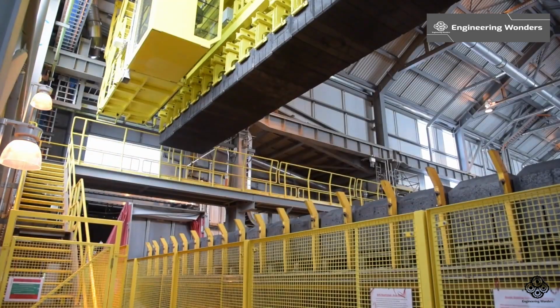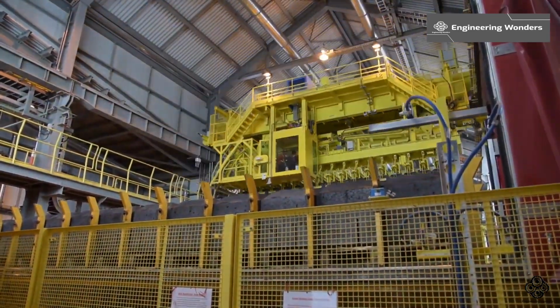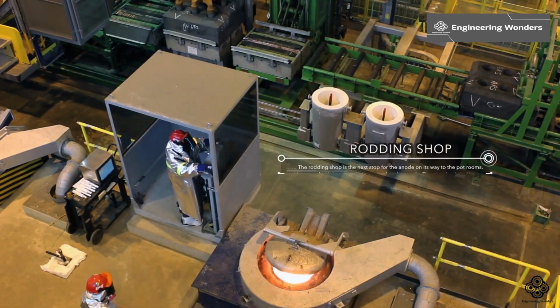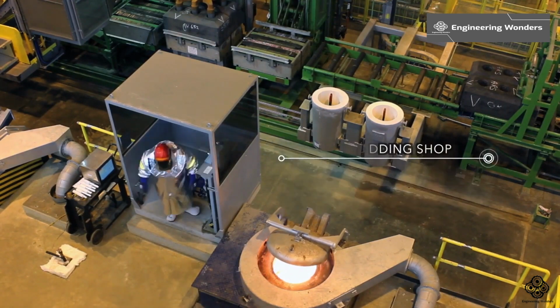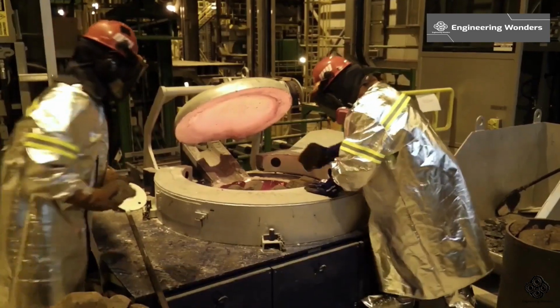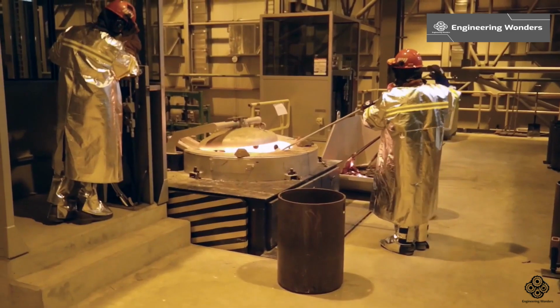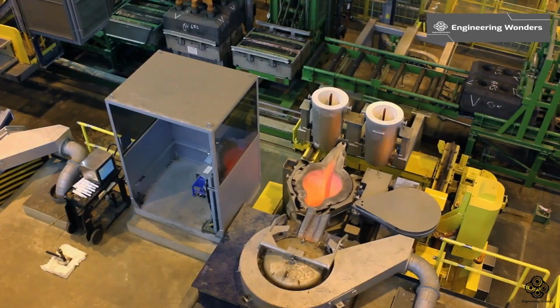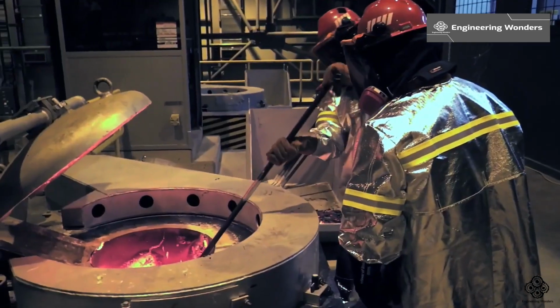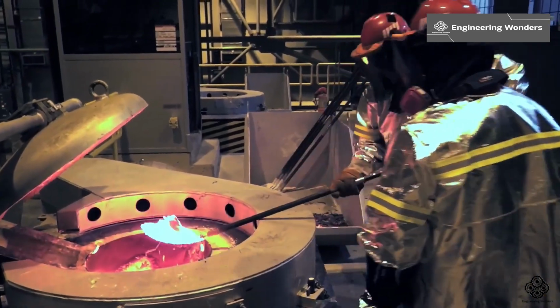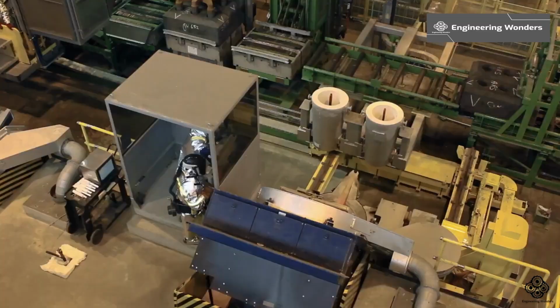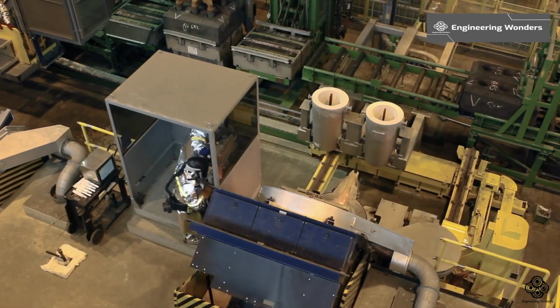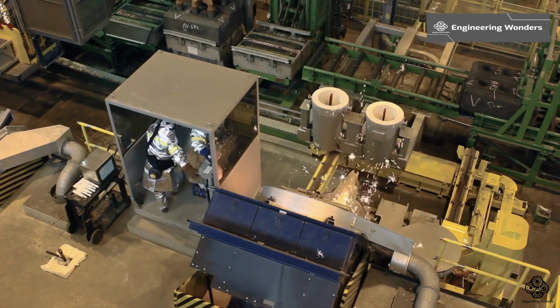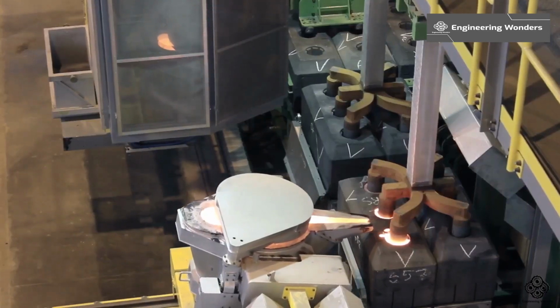Once the reduction process is underway, an electric current is passed through the anodes into the electrolytic bath, where the reduction reaction takes place. The electrical current causes a chemical reaction, separating the oxygen from the alumina in the electrolyte. The oxygen combines with the carbon anode, forming carbon dioxide, while the aluminum ions are reduced and sink to the bottom of the reduction cell as molten aluminum.